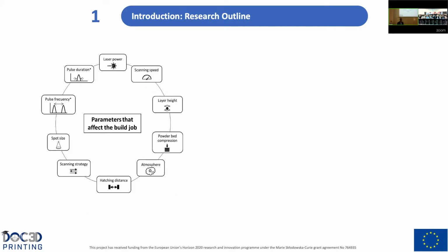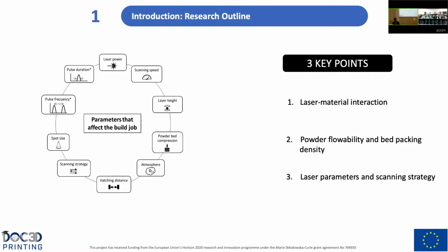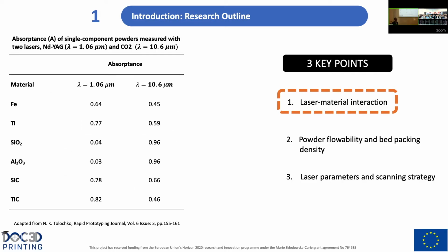So regarding the process parameters of powder bed selective laser processing, there are many parameters involved, and they have an important influence on the final relative density of the part. But actually, there are 3 key points we need to focus on to assure a successful manufacturing process. The first one, of course, is the laser-material interaction. We need to assure that our material will be able to absorb the energy of the laser.